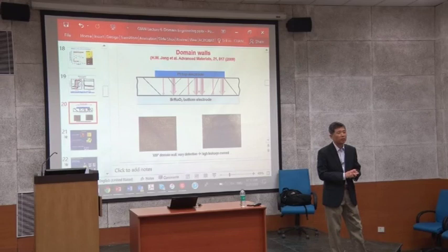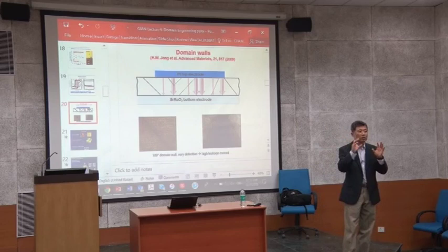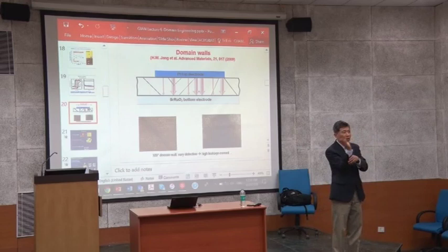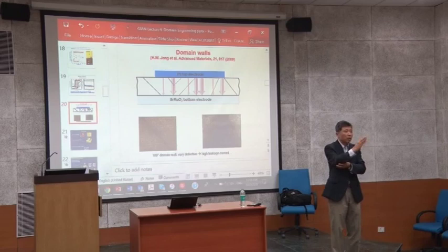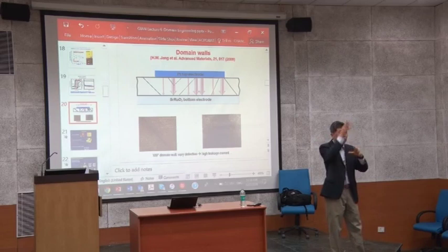Okay. This is something I skip quickly. If you know what the actual distortion is, you can predict which domain forms at what angle and in what direction. So you have a variation of this. For example, you have rhombohedral distortion going in that direction, that direction, and that direction. You pick one reflection which can pick all of those, and which contains a certain HKL component. Because of these different orientation distortions, and your location in reciprocal space, it shows the different regions.